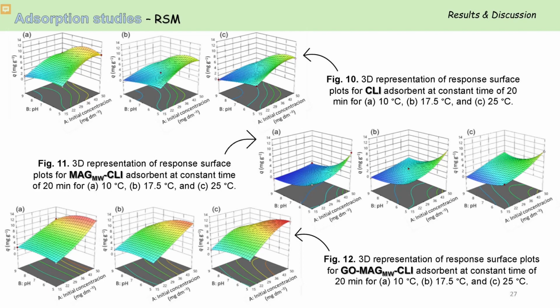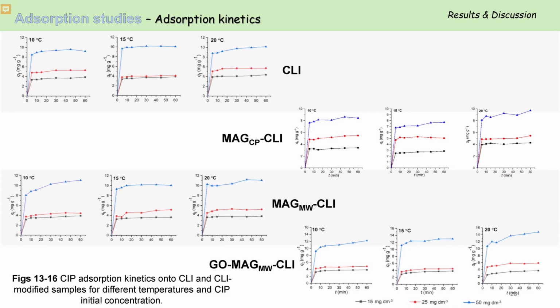As we can see, the adsorption capacity was influenced by the initial concentration. The optimal pH is around 5, and the graphene oxide magnetic clinoptilolite shows the best adsorption efficiency at all investigated temperatures. As for the kinetic results, the adsorption efficiency of all adsorbents increases with contact time, and we can see that the efficiency increases rather sharply in the first 5 minutes and achieves around 85% of the maximum adsorption capacity, which indicates fast adsorption.